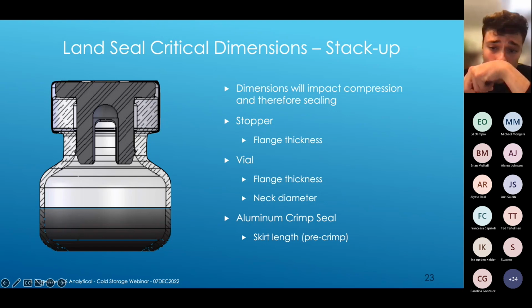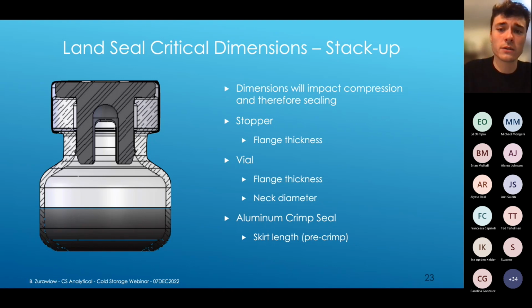And so there are numerous dimensions also that will impact this compression and therefore this seal as a result of that process. So we have dimensions like the stopper flange thickness, the vial flange thickness, the neck diameter, and the aluminum skirt of the crimp seal, all of which, as you'll see in a few slides, can have an impact on the compression of that stopper and therefore the seal of that package system.